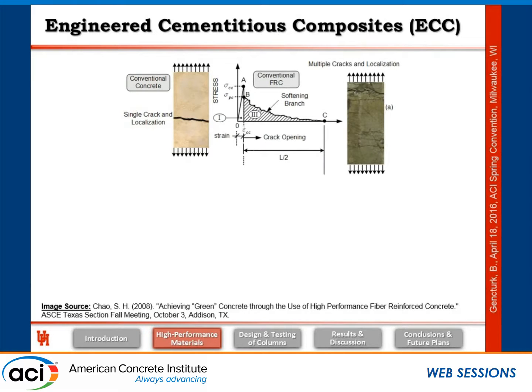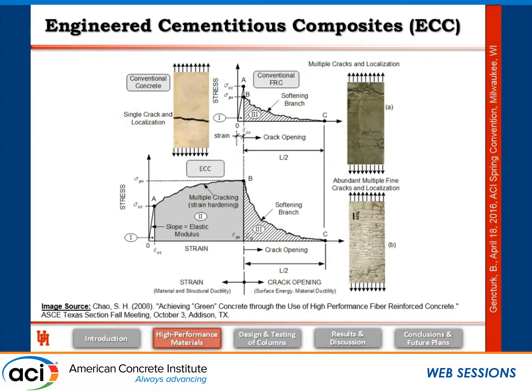If you look at a conventional fiber-reinforced concrete, after the peak, you will see some softening, which is due to these multiple cracks, but still there is not much of a crack distribution and there is still a localized crack. And in the case of ECC, there is a significant strain hardening region, this region, which causes abundant multiple fine cracks. And after that, you again see a localization with a single large crack. But this really happens at a very large strain, and that very large strain depends on who you ask, really, and how you prepare the material. Again, the advantage is in uncracked state, it has lower permeability. And even in cracked state, it has much lower permeability because you directly expose the rebar in most cases in the case of conventional concrete.